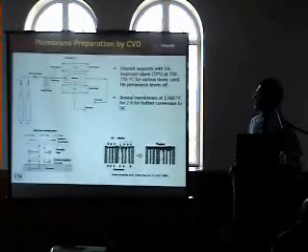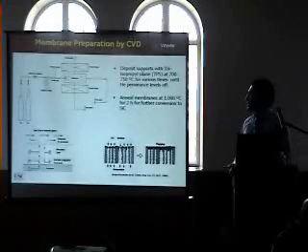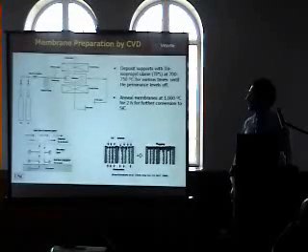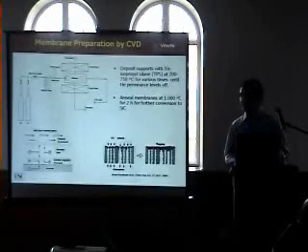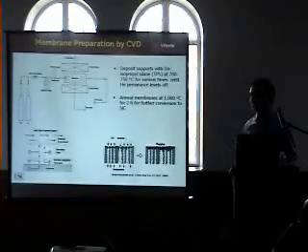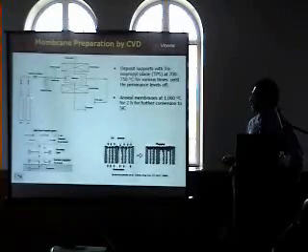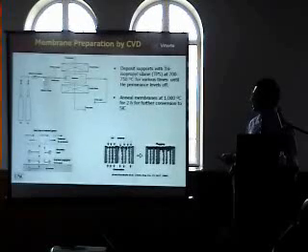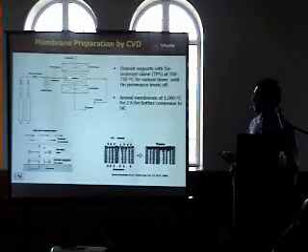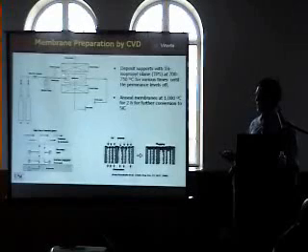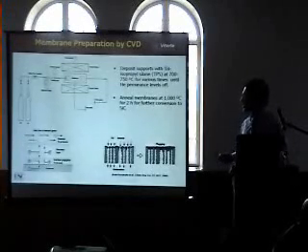The good thing about our support is that it has the same material as the membrane itself, which will avoid any mismatch that might be caused by thermal expansion differences between the two materials. For CVD preparation, we use tri-isopropyl silane as a precursor to deposit on the silicon carbide support at temperatures between 700 to 750°C. The helium or argon carrier gas flows the TPS, which is evaporated, into the reactor, and the TPS decomposes into the pores, forming silicon carbide.